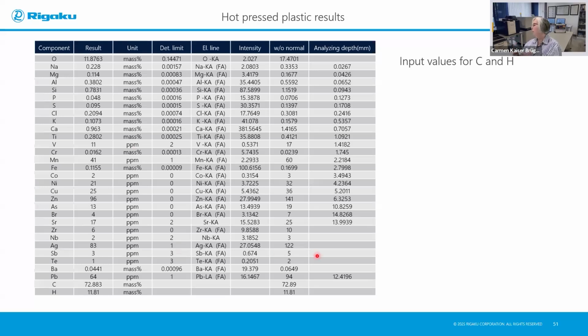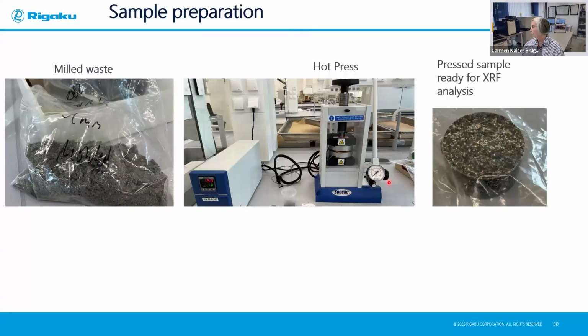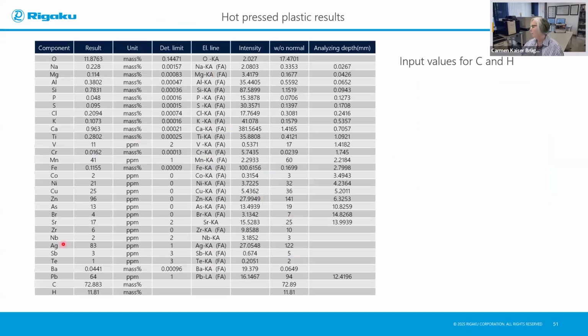So we need to observe and refine the spectra, and of course, always make sure that we have the correct analyzing depth. So please take note, always the heavier elements have a larger analyzing depth, and therefore it's always important that we have this very thick pellet, for the analysis of these heavier elements.